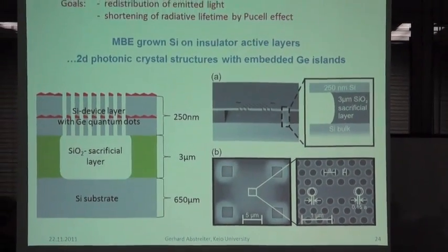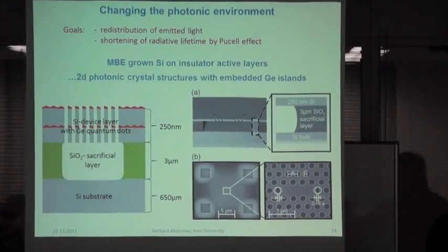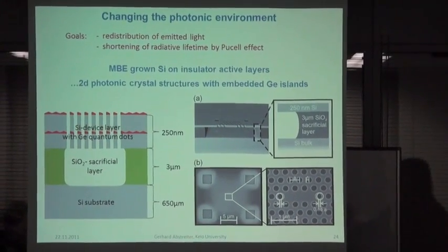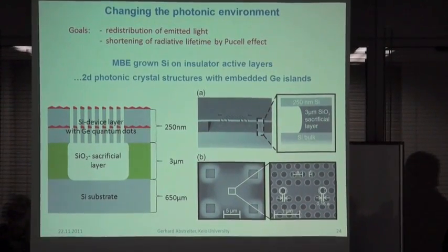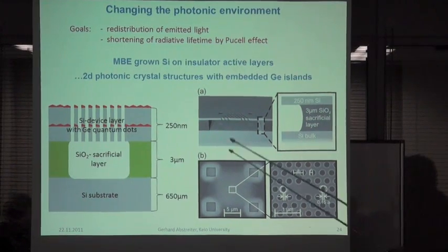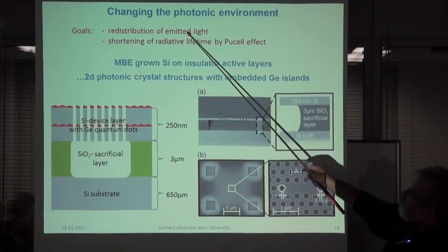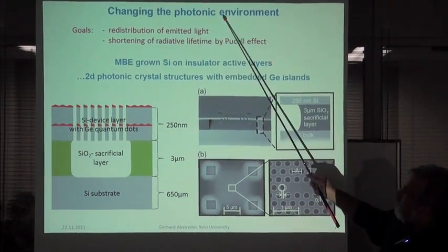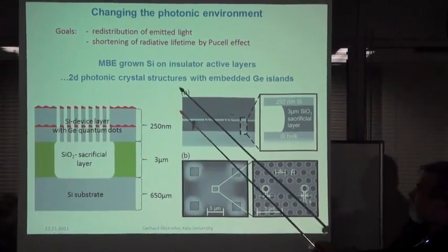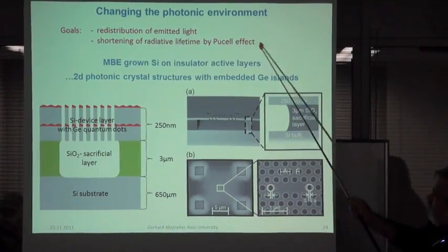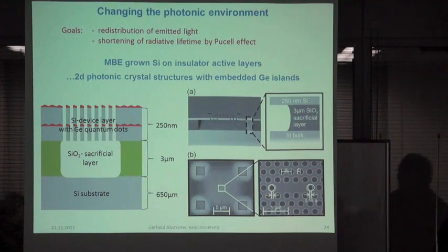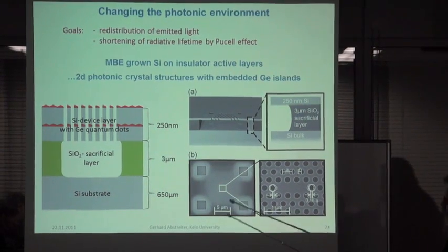But nevertheless, we try to make efficient light emission out of germanium, even though it's indirect in real space and k-space, by redistribution of the emitted light, by bringing it into a different photonic environment, and by shortening of the radiative lifetime by the so-called Purcell effect. And one of the